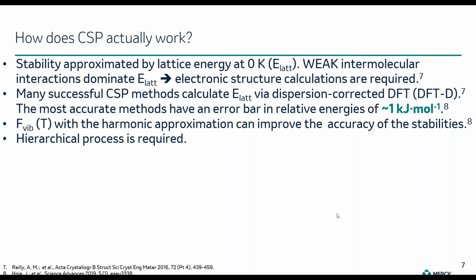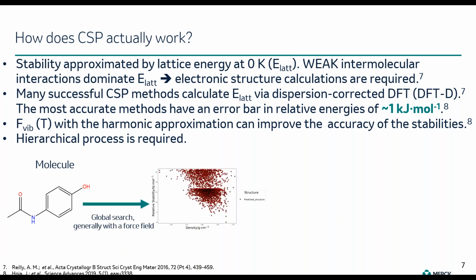However, we cannot get straight from a molecule to a ranking calculated with electronic structural methods. And the CSP generally requires a hierarchical process. So one starts with a molecule and then tends to perform a global search where all the possible packings of the molecules are generated, and a preliminary energy ranking is obtained, but given that the lattice energy surface is immense and that thousands of crystal structures can be generated, this preliminary lattice energy ranking is generally obtained with force fields, not with electronic structural calculation methods.